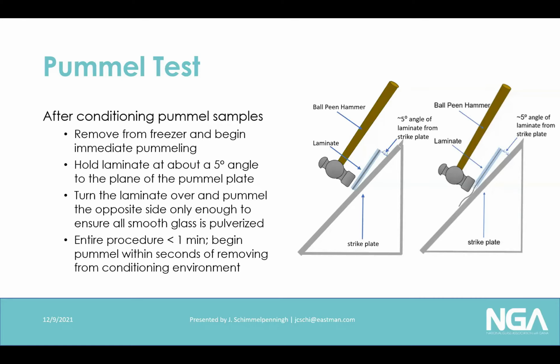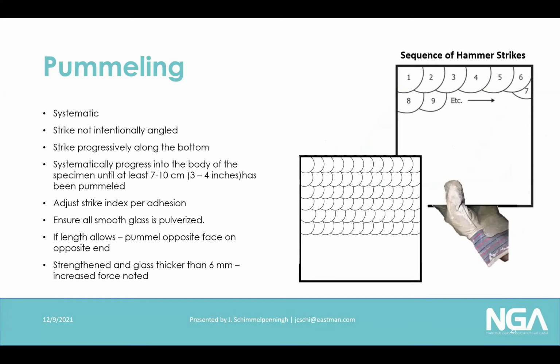So after conditioning the samples, you do pummel them, and we will jump to the video so you can see exactly what that looks like. You're systematically hitting it with a hammer, and the entire process should take less than a minute. So it's very, very quick. You do pummel systematically. As you can see, the hammer hits, that's what this is showing.